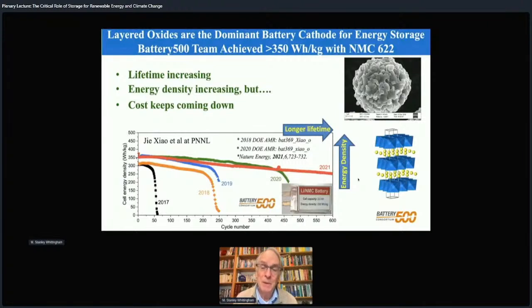This project has just been extended for a second 5 years. So we're now going after 500 watt hours per kilogram. Again, using these layered oxides, but also using a much lower cost and higher energy density system in principle, and that is lithium sulfur. So sulfur is essentially free. Lithium sulfur will today give you about 400 watt hours per kilogram, but it's low on volumetric energy density. But there's serious technical challenges because sulfur is an outstanding ionic and electronic insulator. So it's difficult to get materials to react.